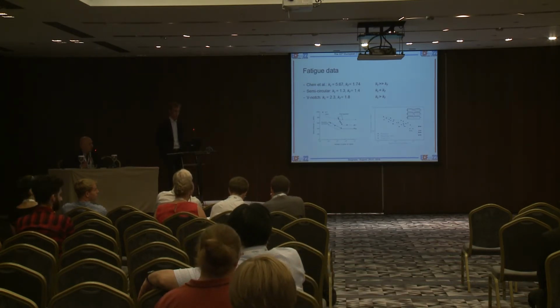And another question, if I may, did you see a difference in surface roughness because you printed them vertically in the notch? I would expect that the overhang part is different than the underneath part. Yeah, there is a large difference in surface roughness. And will this affect the result of your test in any way? I think it will not affect, because the surface roughness is one thing, but it's always initiating from lack of fusion defects, which are acting as cracks, and I think those will be more dangerous than the kind of wavy surface, which will just act as a notch. But for sure the specimens will be failing from the area where you have printed the overhang.